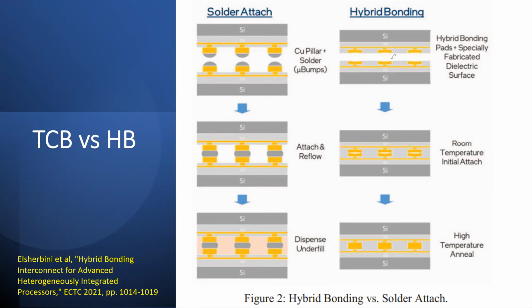And hybrid bonding, on the other hand, doesn't have that. They're missing the solder bond. It's just copper to copper. And then they attach at roughly room temperature. And then you have a high temperature anneal to get rid of the voids.